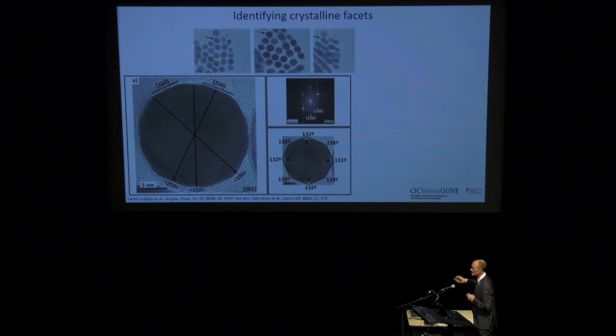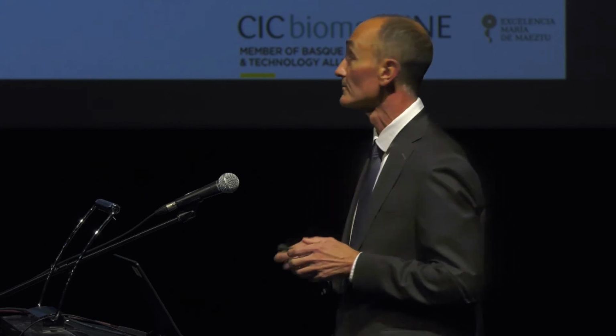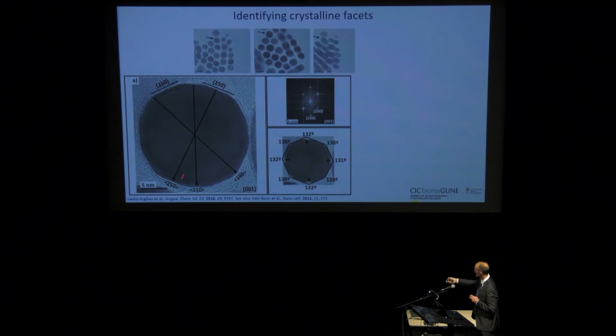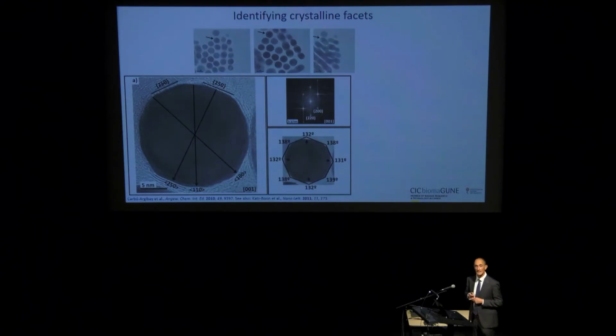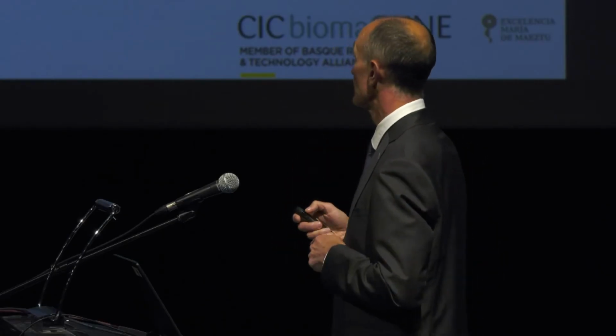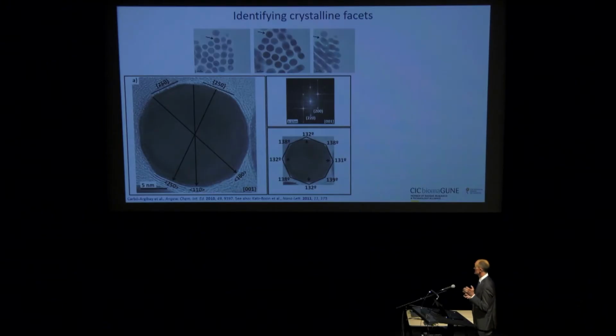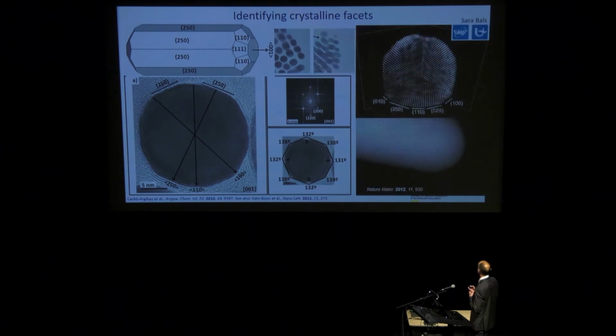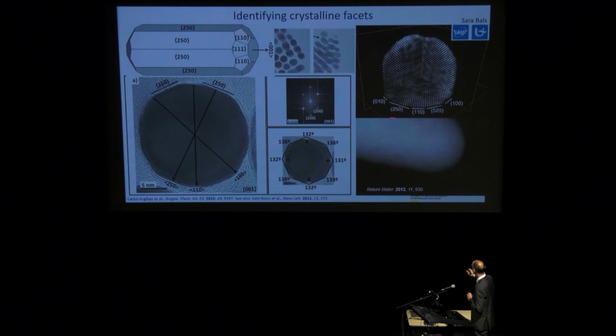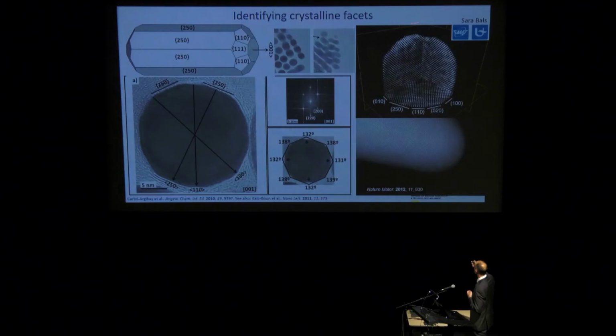And then by doing electron diffraction or FFT, fast Fourier transform, you can see that the lines connecting the lateral facets do not correspond to 100 or 110. They correspond to higher index facets that were not identified before. Coincidentally, my friend Paul Mulvaney was doing exactly the same thing at his lab in Melbourne, together with people at a neighboring university. And this has been corroborated now by a few other scientists. Also, in our collaboration with Sara Bals in Antwerp, they can do atomic resolution electron tomography. They are able not only to see projections with atomic resolution, but to turn the nanoparticles and reconstruct in 3D the position of every atom and identify the facets and the tips.